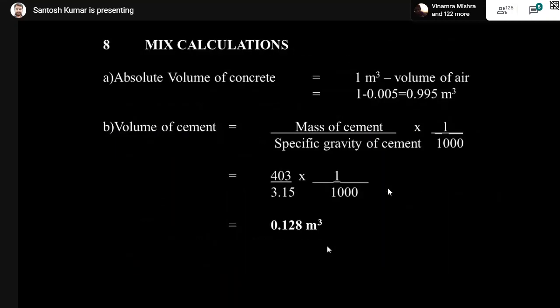Now we calculate the absolute volume of concrete by removing the air content. The volume of air, with 0.5 percent of air, means the volume is 0.005. So 1 minus 0.005, that is 0.995, is the total absolute volume of your concrete. So the volume of cement is calculated by the mass of cement, which is 403, divided by the specific gravity of cement, multiplied by 1 by 1000.